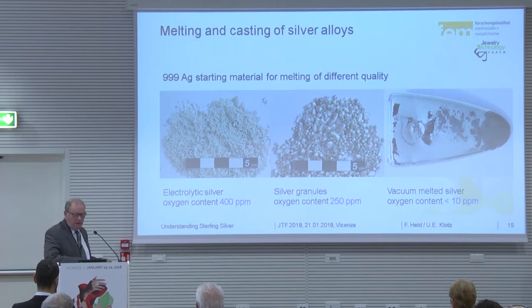you only have 200, but you also can have 300, 350 ppm oxygen. Best material is if you use vacuum melted silver, the oxygen content is smaller than 10 ppm, but most people will use granules and make the alloys themselves during melting.